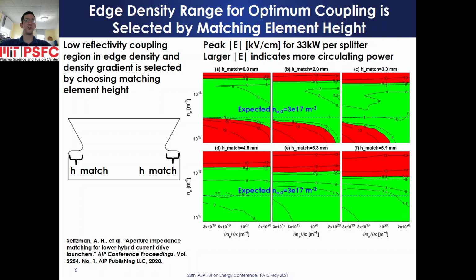A high field side edge density of 3 × 10^17 per cubic meter is expected in D3D target discharges. By selecting an appropriate matching element height, the optimum coupling region, shown on the right, indicated by lowest electric field within the vacuum region of the launcher, may be centered around the expected edge density. In this manner, a launcher may be specifically designed for the predicted edge conditions.